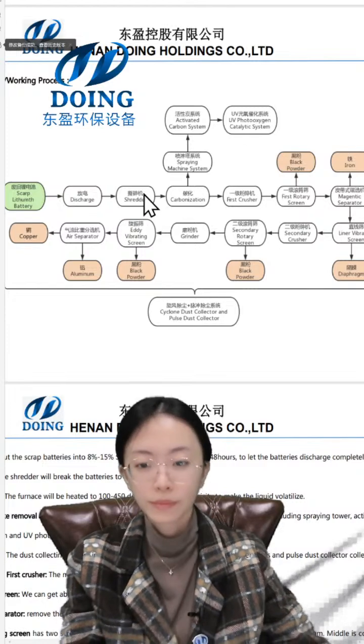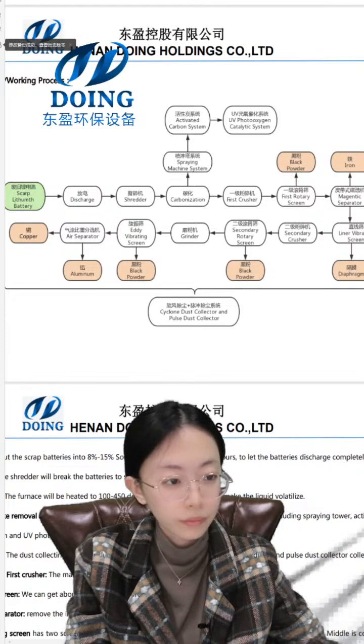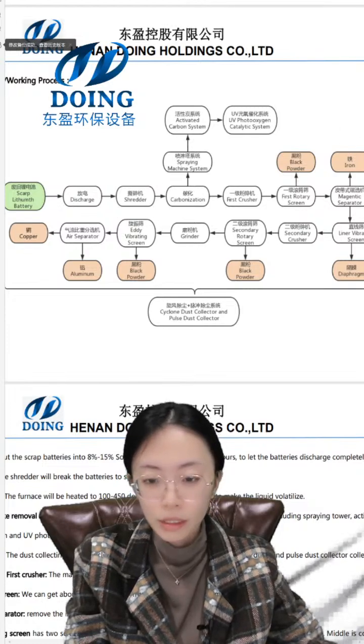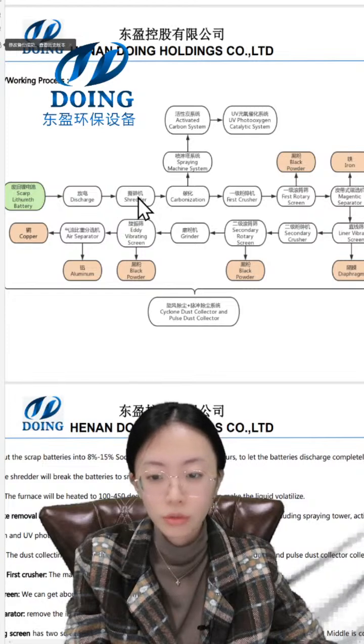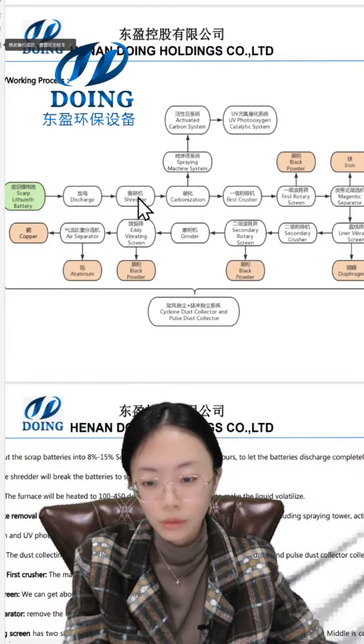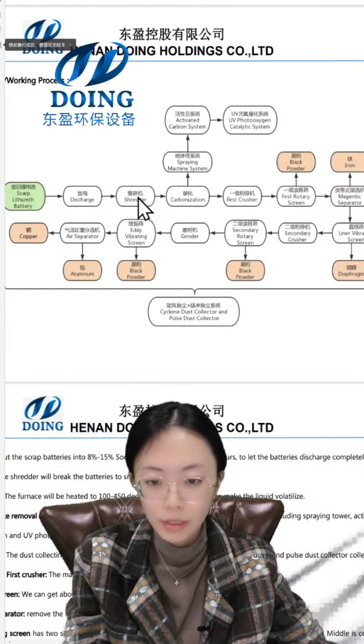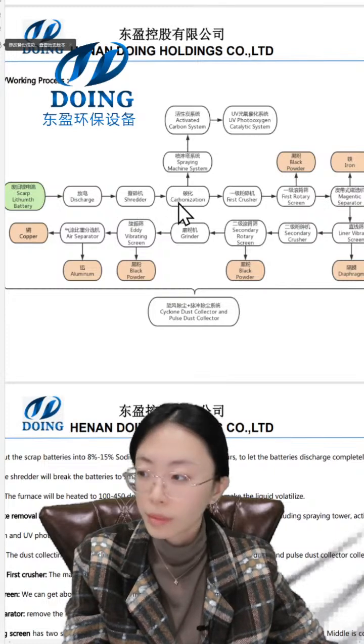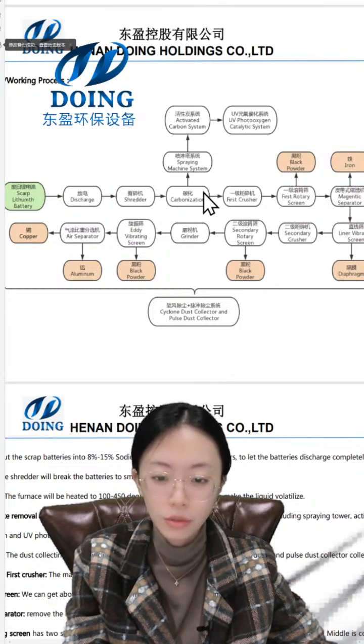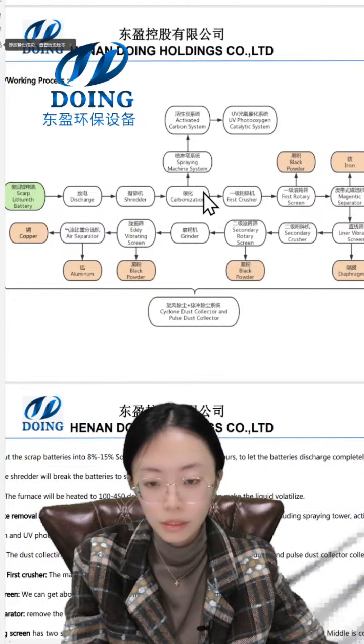In this step, in the double shaft shredder, the material is shredded to 3 to 5 centimeters, and then it comes into the carbonization furnace to be dried. The temperature is almost 100 to 200 degrees.